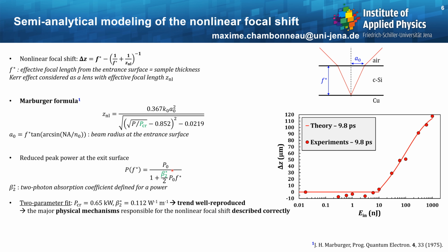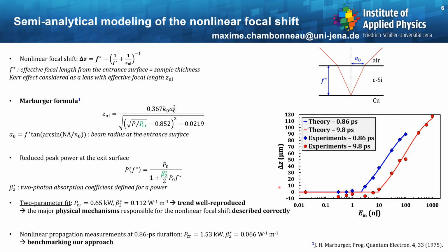And with this two-parameter fitting procedure, we can compare some calculations to the experiments, and as you can see here, the trends are very well reproduced, meaning that the major physical mechanisms that are responsible for the nonlinear focal shift are correctly described. Moreover, we have carried out additional experiments with another pulse duration here in blue. The pulse duration in this case is 860 femtoseconds, and well, the results are essentially the same. I mean, the trends are also well reproduced, meaning that our approach is benchmarked.